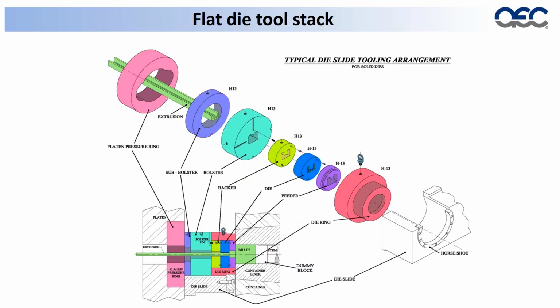But if you take a look at the way this tooling is designed, the thing you notice is you have immense pressure on the front face, and then each part behind it gets bigger and bigger and bigger. And what that does is increase the amount of contact square inches so that this pressure can be dissipated out to the press at the very back end, because nothing will withstand direct 98,000 pounds per square inch pressure right on its face, and it'll push right through the same way that the live end of a bullet gets pushed out through a barrel on a gun. It's got to be dispersed, and the various square inches has to be increased so that we can dissipate it.